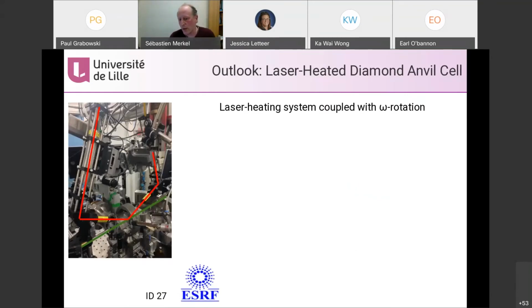But as you saw, it's a very interesting result, but we were limited in the pressure and temperature range. We couldn't work on the true perovskite, post-perovskite that we wanted to, that would be relevant, that will be the one you'll find in the Earth's mantle. For that, you need laser heating, and you need to be able to rotate your diamond anvil cell in front of the X-ray beam while collecting X-ray diffraction. And it's actually possible now. I mean, it was before the ESRF went for repairs, they just installed it at ID27. They just installed a system like that, and we're lucky enough to use it.